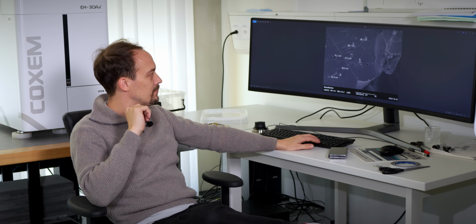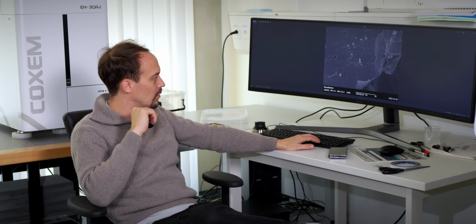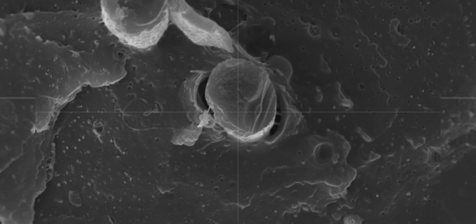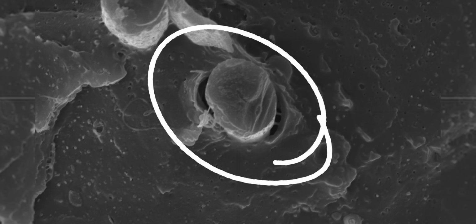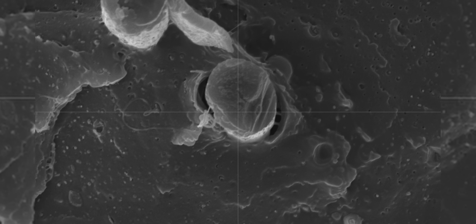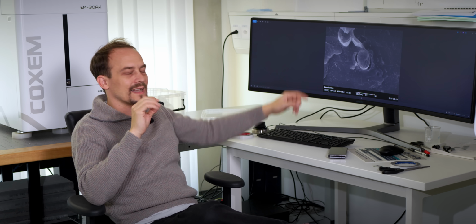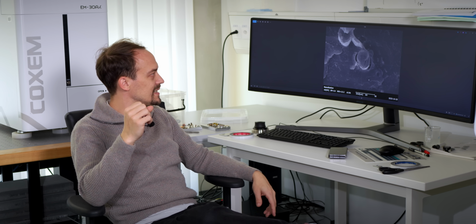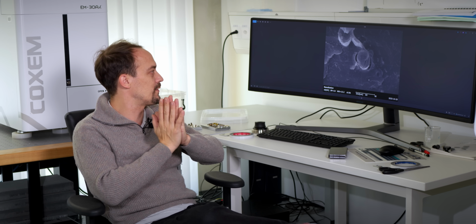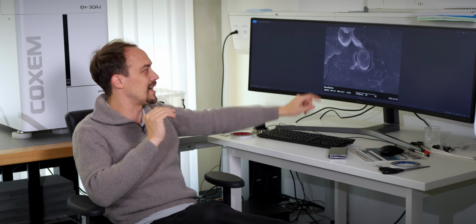But one very interesting thing I saw here, even better than in my carbon fiber PLA videos, is if we zoom a little bit in on especially this one, then if we get closer and closer, first of all, we can see that up here, the carbon fiber actually detached from the polymer while breaking, and you can still see the surface pattern on the polymer, and you can still see that it matches the other one perfectly, but I want to concentrate on this carbon fiber.